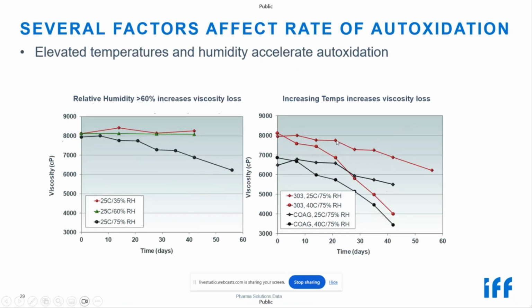So 25C in diamonds, we have 40C in the circles, and we can see how just raising temperature from 25 to 40C, we see a drastic drop in the viscosity over time. Same thing for the coag. Diamonds are 25C, circles are 40C. We see an increase in that viscosity loss over time. So increased humidity, not good. Increased temperature, not good.